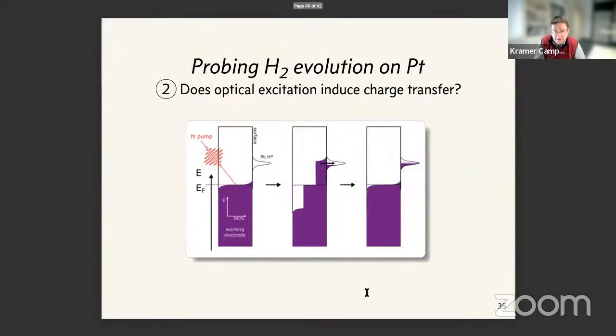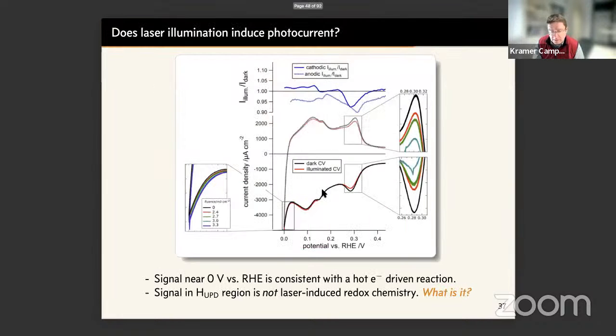The picture is, if we look at this picture, right, you can satisfy yourself of this. From the point of view of the laser and the electronic structure of platinum, the scan direction doesn't matter. And so the idea is, of course, that this pump pulse should excite the anti-bonding platinum hydrogen orbital going in both directions. And if this is being populated in both directions, the current is flowing in only one direction, right? If we're driving this kind of electron transfer induced chemistry.